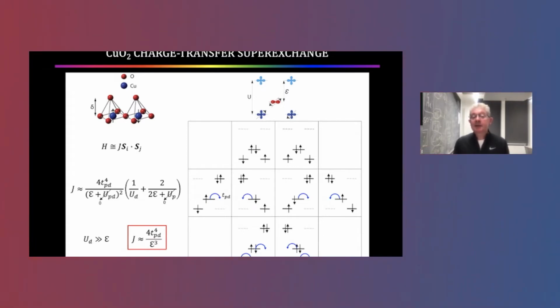That is in the case that the Coulomb energy, the Hubbard energy, is much bigger than the charge transfer energy, and there's many transition metal oxides where that's not true, but for the cuprates it is true. U is much bigger than epsilon. In that case, the superexchange energy, in perturbation theory, is 4 times the pd hopping rate to the power of 4 divided by the charge transfer energy cubed. That tells the strength of superexchange between adjacent spin-a-half electrons on the copper sites.